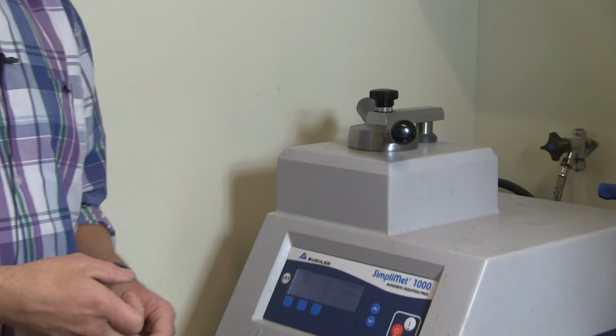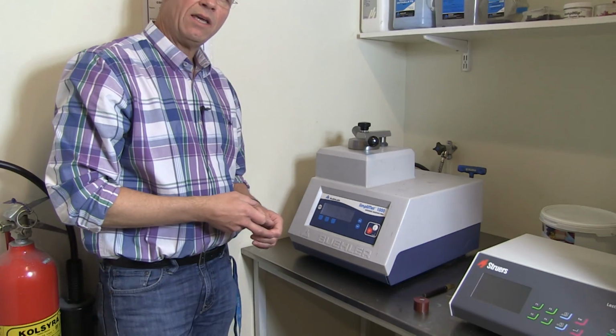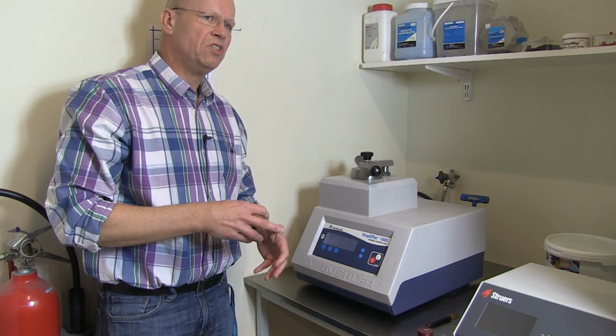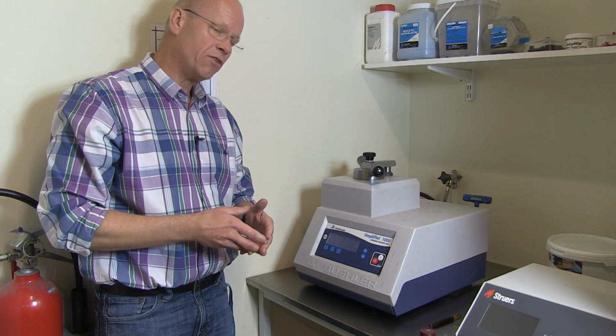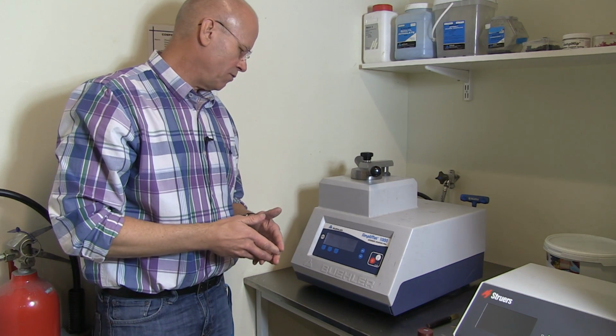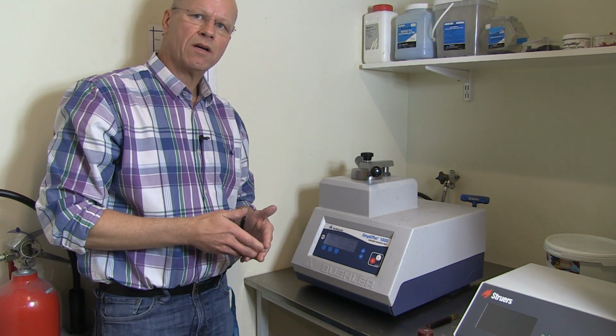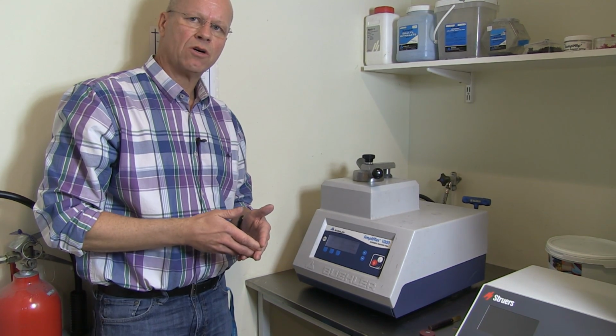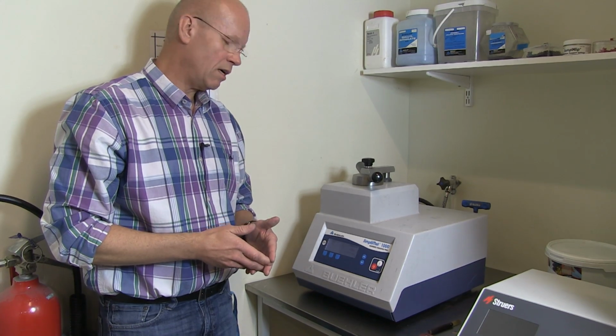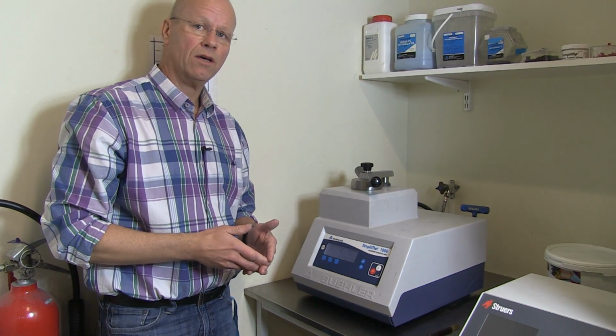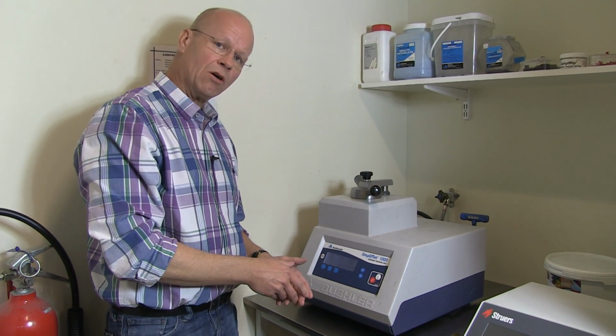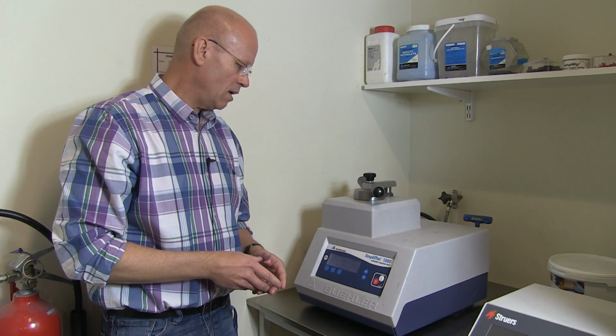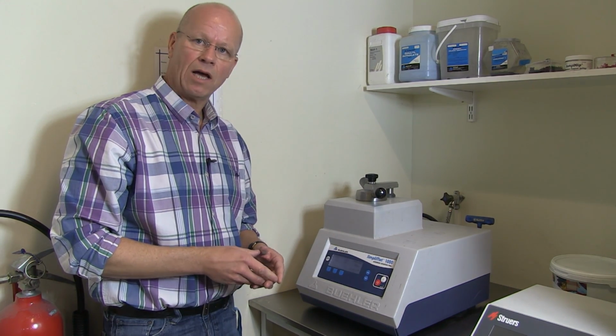So now pressure is applied, it's preheating. In 6 to 8 minutes it will reach 150 degrees. After that it will keep 150 for 1 minute, and then start cooling and cool for 3 minutes, and then a short signal will sound, and the text cycle complete will come up on the display. I will show you then how to take the sample out.